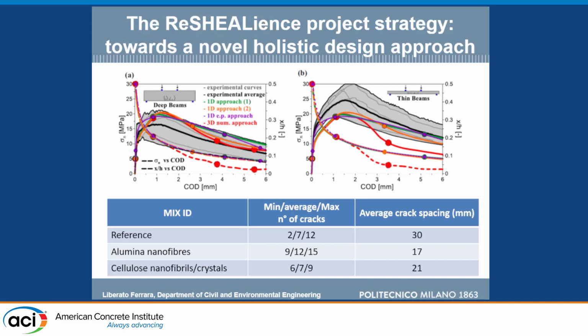And what we get, interestingly, was, if you look at we have a 4-point bending test, so you can imagine that in the central part of the beam, you have multiple cracking. And this is the key of this material. Multiple cracks, each one is very, very narrow, very tightly open, and it's good for durability. With the reference material, the average number of cracks was 7, ranging between 2 and 12 according to the specimen. When we added up alumina nanofibers, we had much more cracks in same zone, which were tighter spaced.